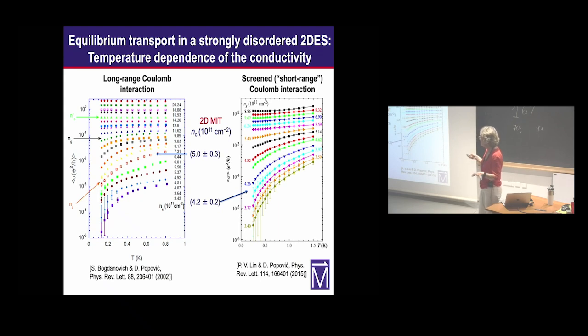At high densities, the temperature dependence is very weak, and this has been known for decades in these strongly disordered silicon MOSFETs. As we reduce the carrier density, the temperature dependence becomes stronger. You can see that at the lowest densities, it's exponential in both cases, and both systems undergo a metal to insulator transition at critical densities that are comparable. So I don't have time to show you in detail how we determined the critical densities, but I will just summarize what we have done.